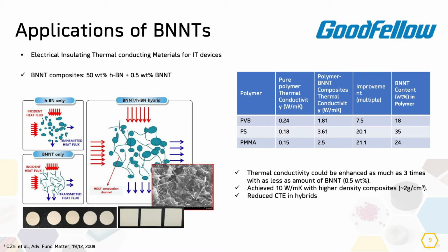This has been measured with the microthermal mechanical analysis, and this is very important for IT devices because they reduce the thermal stresses in a printed circuit board, for example, which is laminated. Also, I would like to say that this thermal stress is very important because it can lead to failure of this PCB that we have in our IT devices. So the boron nitride nanotubes will offer great opportunity and a great result in this occasion.